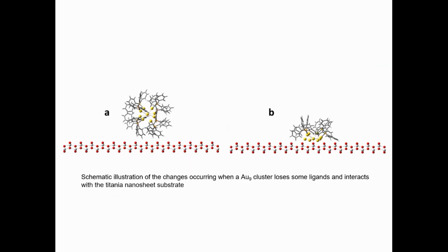Which means that at the beginning, we have a 3D structure with the ligands. When it interacts with the surface or the ligands are removed, the structure of this nanocluster changes. We also deposit them on the P25, which is the titanium dioxide (titania) nanoparticles. And we can show a difference before removing the ligands and after removing the ligands, and we saw some aggregation. And this is also the STEM images. The large one is the P25, and this one is the gold 9 deposited on top of the P25, which is the titanium dioxide (titania) nanoparticles.